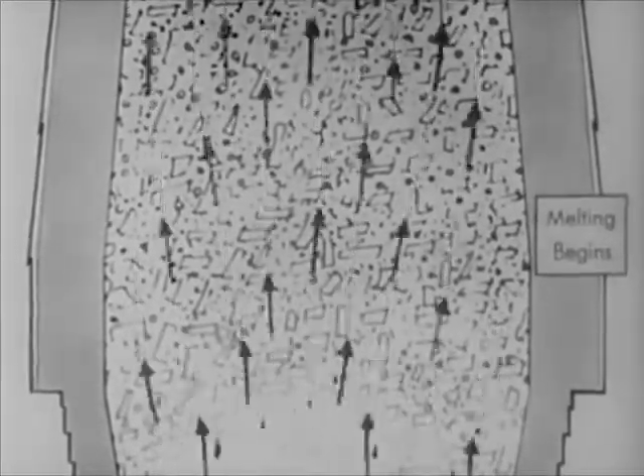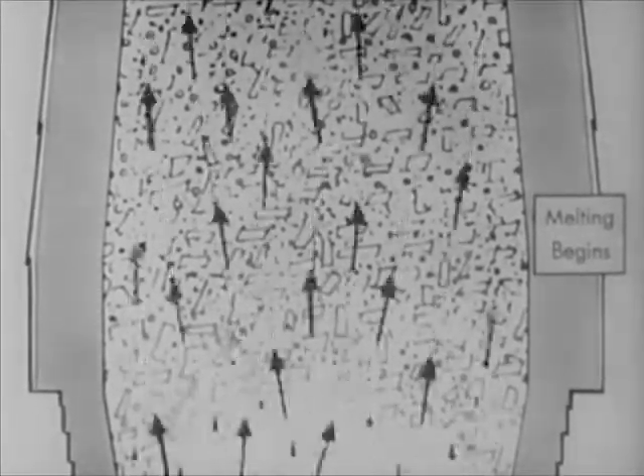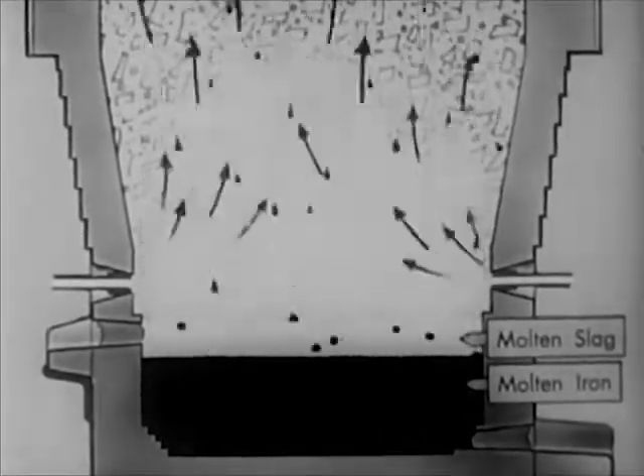The charge descends through increasing heat until at about 2,000 degrees, the spongy metal absorbs about 3.5% of carbon from the coke. Continuing to descend at about 2,500 degrees, the iron with the absorbed carbon melts. The limestone combines with the earthy matter of the ore, forming slag. The iron and the slag form in molten globules like raindrops, which trickle down through the burning coke. A pool of molten iron is formed on the bottom of the hearth. The slag floats on the iron and is drawn off from time to time.